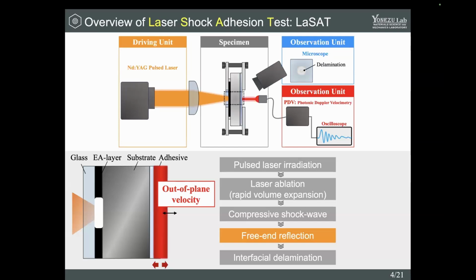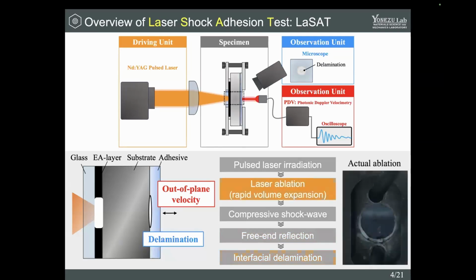At this time, the arrival of the shock wave causes the free surface of the specimen to vibrate slightly. The vibration velocity, the out-of-plane velocity, was measured by PDV. And finally, after this wave propagates through the interface again, the delamination occurs. The delamination was observed directly in real time using a digital microscope. This is an actual laser ablation.